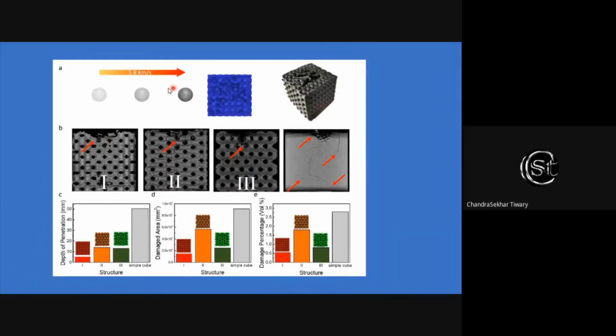So what we do is use 5 kilometer per second bullets to hit this structure. And then after the impact, we have done X-ray imaging just to understand the cracks and so on. And if you see the structure here shown by the laser pointer, if you take a solid block and you impact, you can see a lot of cracks generated. What it means is the bullet has transferred all the energy till the bottom, and that's the reason you get the effect of this impact. Whereas if you make this kind of structure, you can see the bullet or energy got trapped wherever it hits.